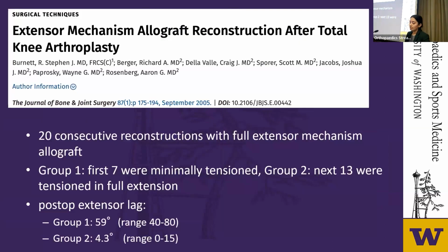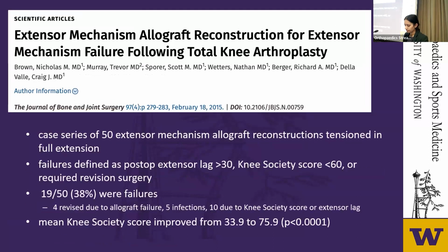And just a few studies on the full allograft. So tensioning of the allograft is an important aspect of surgical technique. The study in JBJS in 2005 compared two tensioning techniques in a series of 20 patients who underwent full extensor mechanism allograft reconstruction. So the first group was the first 7. They had their allografts minimally tensioned, and the second group had them tensioned in full extension. And all the reconstructions in group 1 were clinical failures, with the average post-op extensor lag being 59 degrees, while the group 2 extensor lag was only 4.3 degrees.